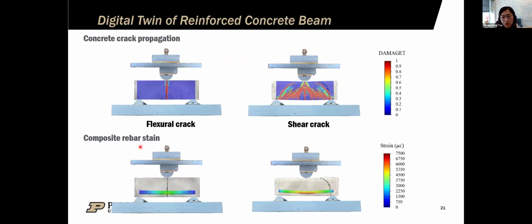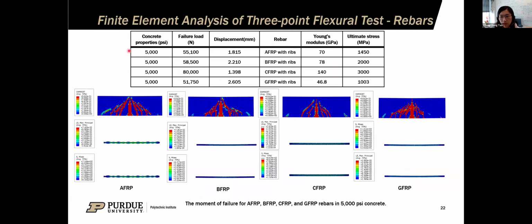Through the experimental and the numerical investigation, we developed a digital twin model for the reinforced concrete beam system, and we can generate a big data set for AI-based condition assessment and optimization. So here are some more results, like using the finite element analysis to generate a larger data set by considering different rebar types: AFRP, BFRP, CFRP, and GFRP. We also change the concrete properties and the rebar rib properties to generate a very large database.